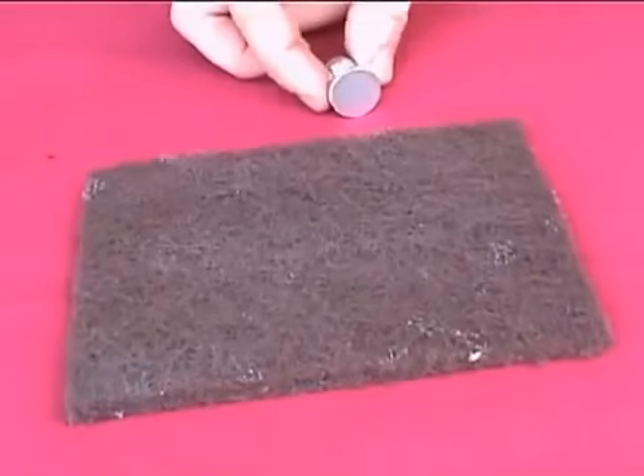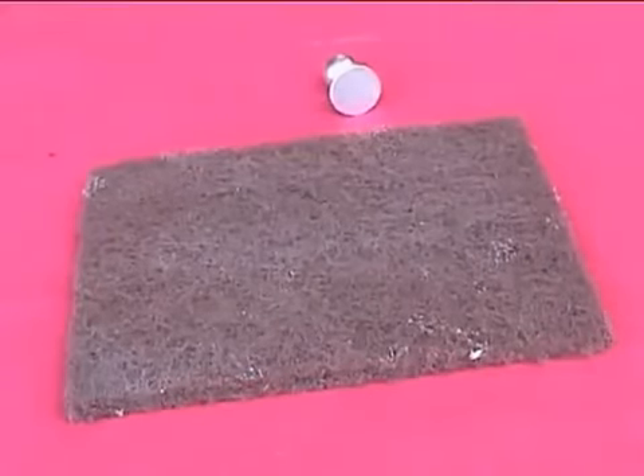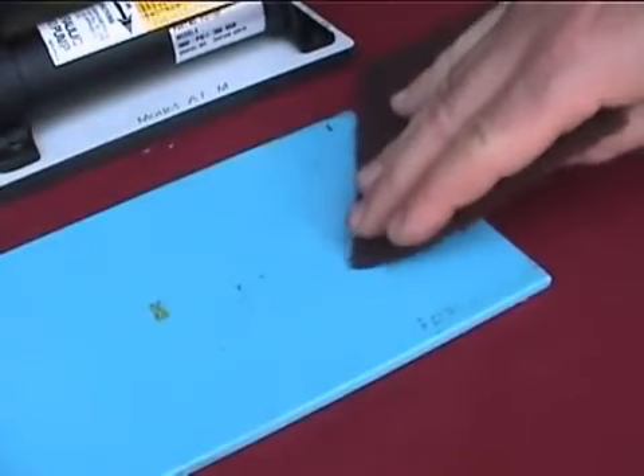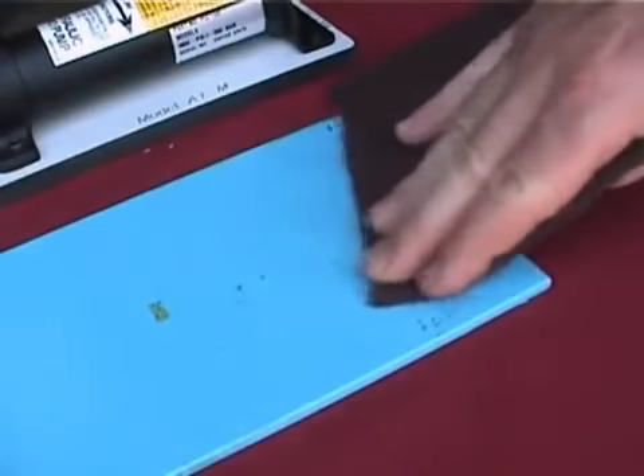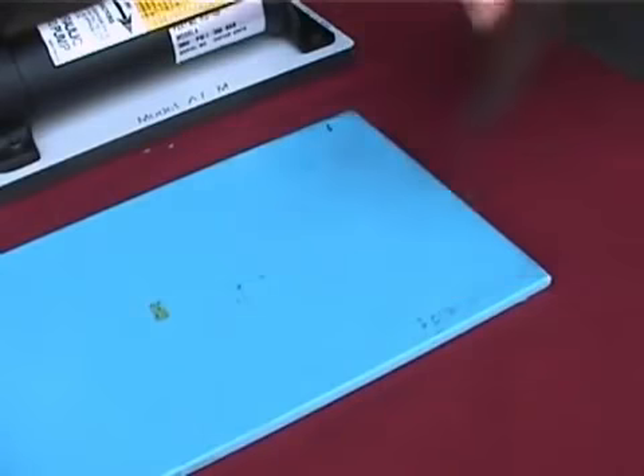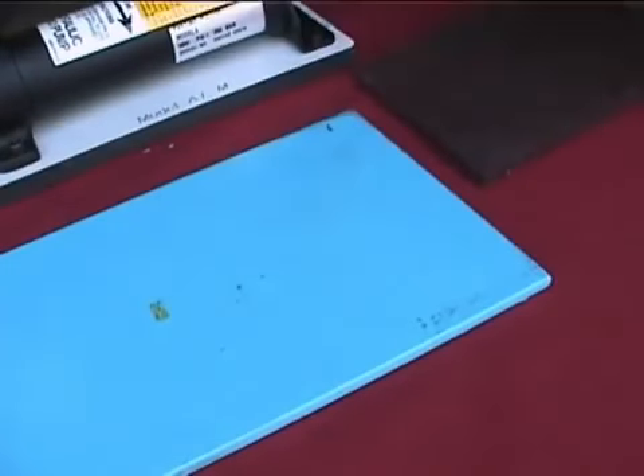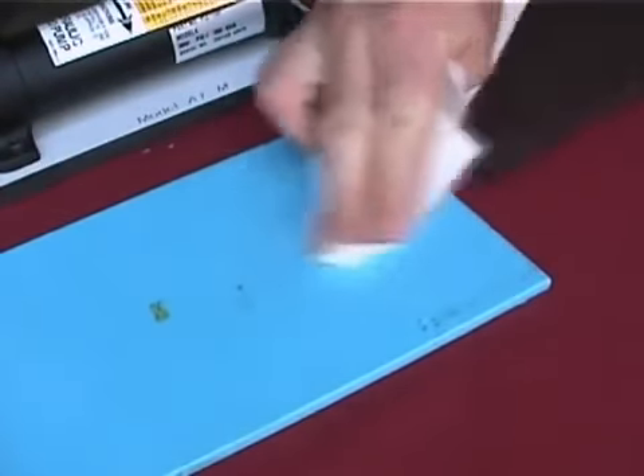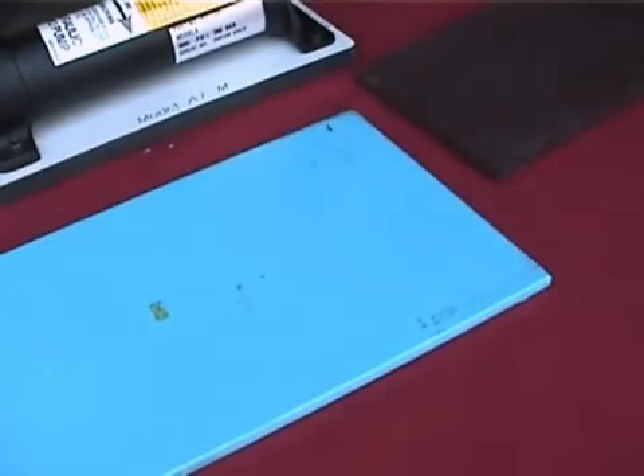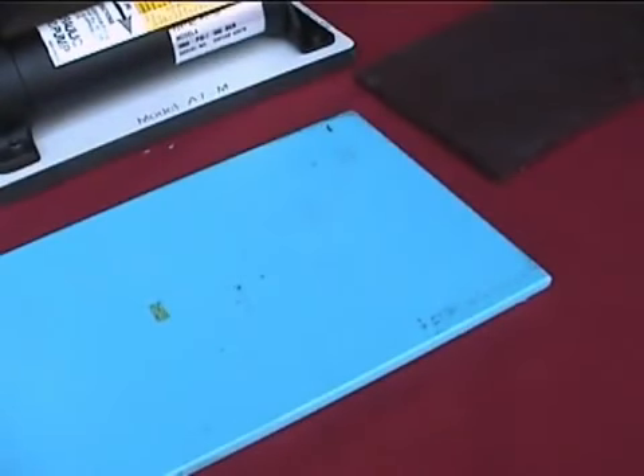When preparing coating surfaces, the challenge is to prepare a clean surface that will readily bond with the adhesive without changing the properties of the coating. Each coating will vary, as will its preparation method. Preparation may range from wiping with a dry cloth to degreasing with alcohol to gently abrading to promote adhesion.